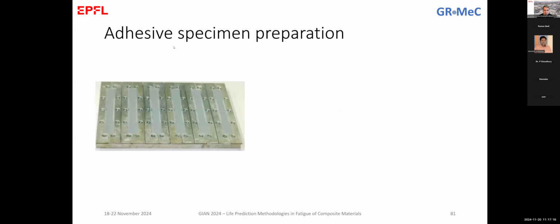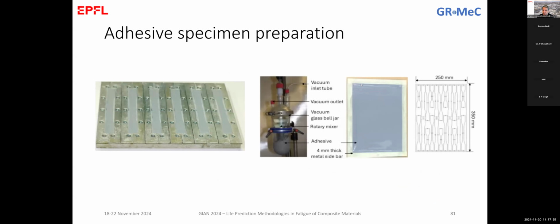So how we prepare the specimens, we have either steel molds or plastic molds, and we can pour the material in the mold and carefully work with a spatula there to spread the material well. Another way that you can do is to prepare a plate with a certain thickness that you need, and then you can cut your specimens with a water jet cutting machine. And this is probably more accurate than this method, and it's also simpler to do. But again, for both methods, there are advantages and disadvantages. So we used both, and we have results with both methods.